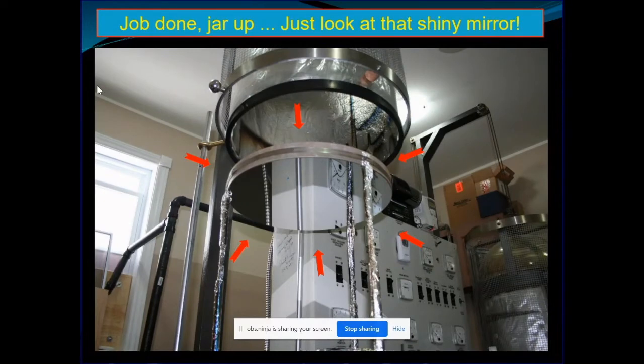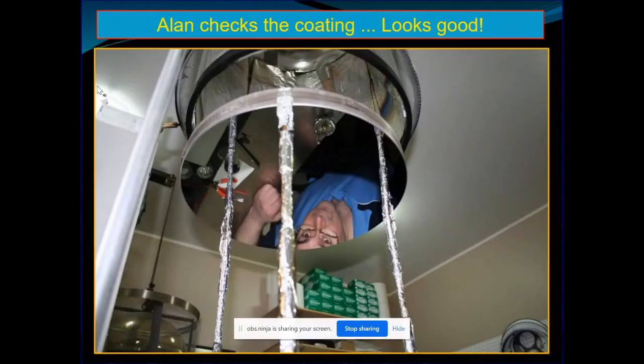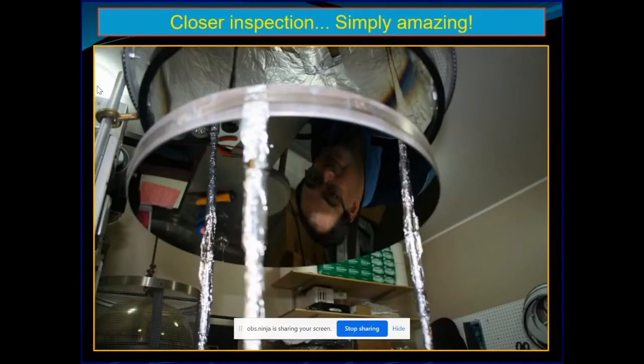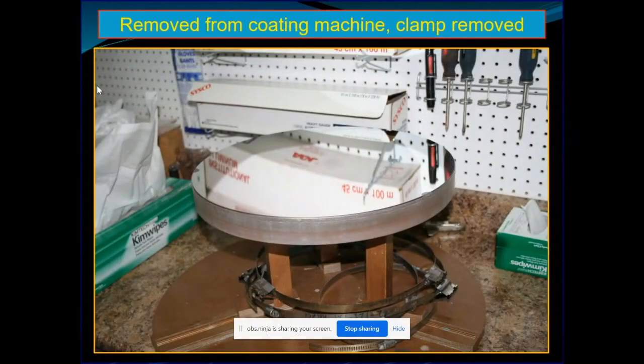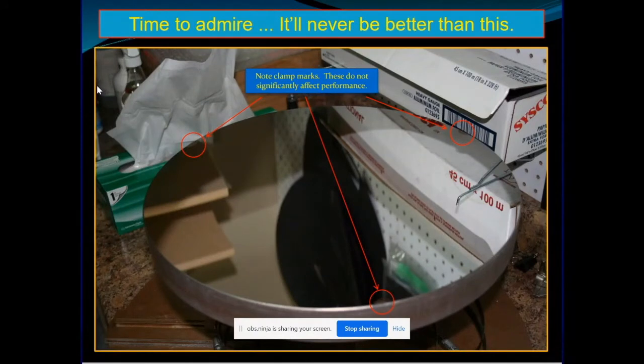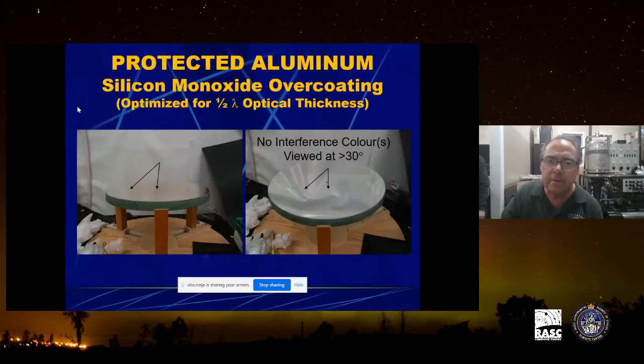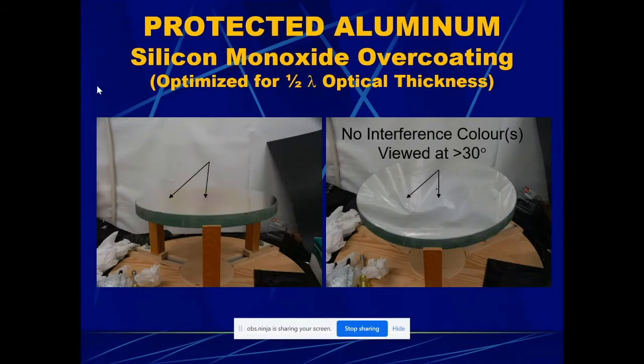So this is the mirror that's just being coated. Now, when you look at a mirror that's being coated, and if it has overcoatings on it, you'll see certain features on it. And these are interference colors that you will see. And so one of the things that we do, these coatings have to be baked at a very high temperature in order to be cured properly. So they're baked in air in an oven at about 250 degrees Celsius in order for the coatings to cure.